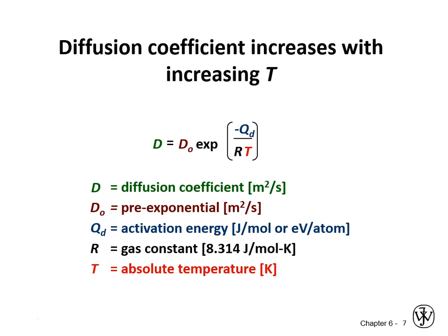To a much lesser extent, interstitial diffusion is temperature dependent, and will have some dependence of its activation energy on vacancies simply because the lattice is more wide open, but not to the extent of substitutional. You can literally think of the activation energy for substitutional diffusion in metals as being a combination of your activation energy for vacancy creation and then another activation energy that represents the jump frequency of those atoms trying to jump from one position to the other.